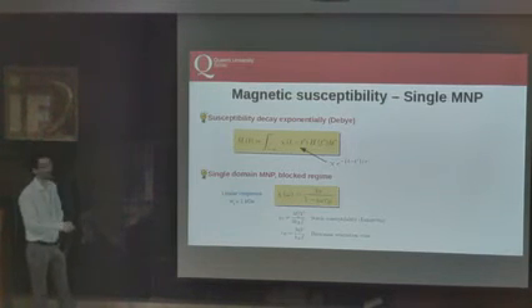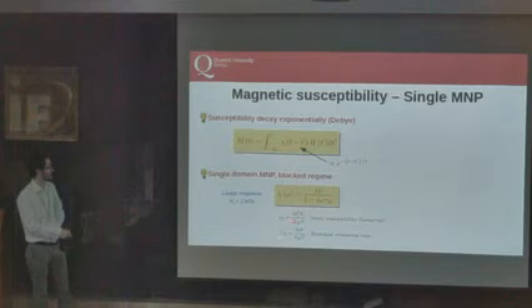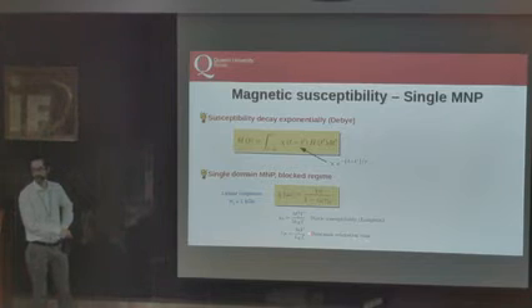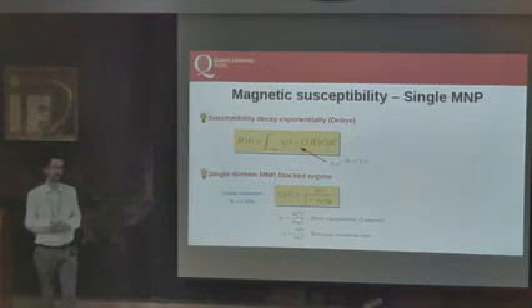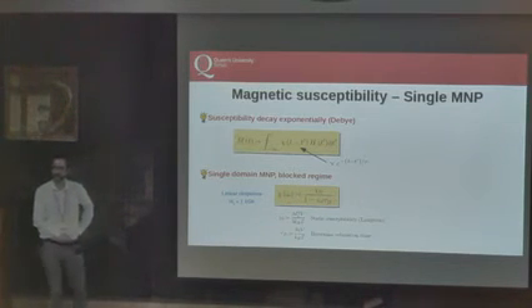And this exact solution is the equivalent of the Debye theory of relaxation. And if you haven't seen this form, it is exactly the same as the Debye model. Terms, of course, change slightly. What is the Debye relaxation time? Here it is called the Brownian relaxation time. Again, it depends on the volume of the nanoparticle, the viscosity, so this is 0 for 0 viscosity, and the temperature. And then if you have some acquaintance with magnetization, this is nothing else than the static Langevin susceptibility.